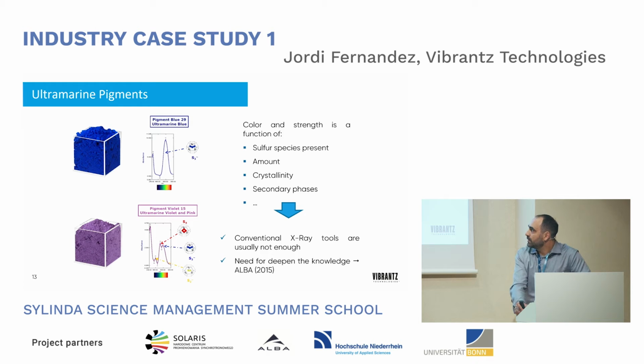On the other hand, ultramarine violet and pink are made through a combination of several different chromophores. S3, the blue one. S2 is another anion radical species that gives some yellow color, and S4 gives some red color. So the combination of red and blue gives the violet, and reducing the blue and increasing the red, at the end, you obtain the ultramarine pink.